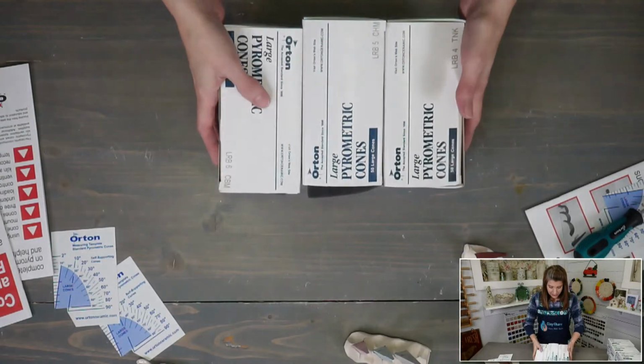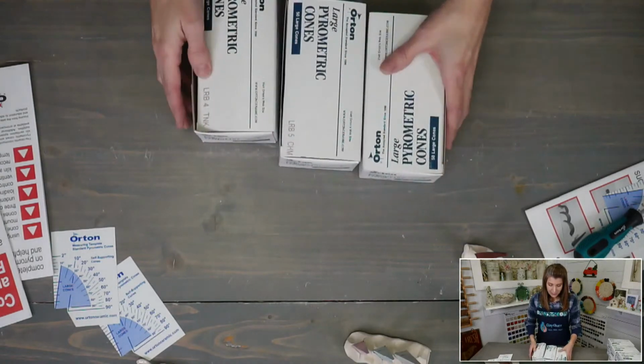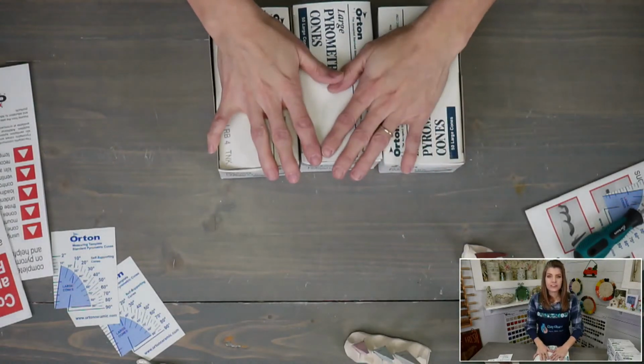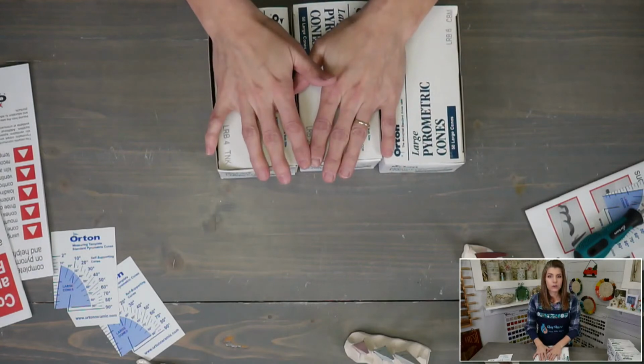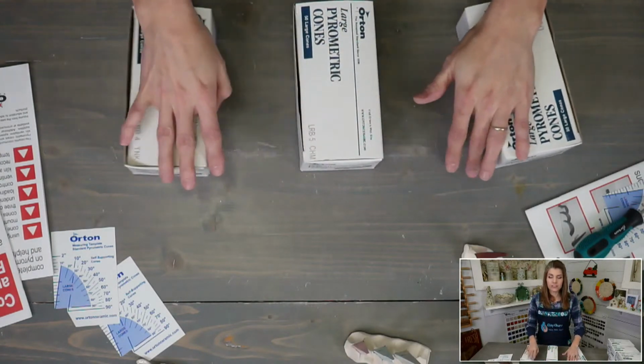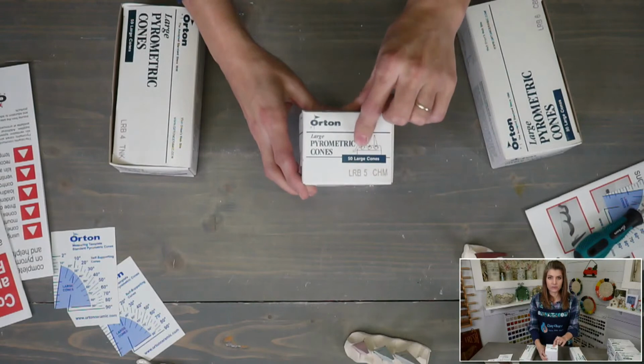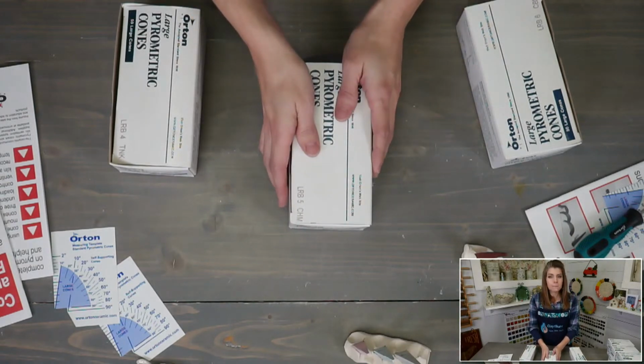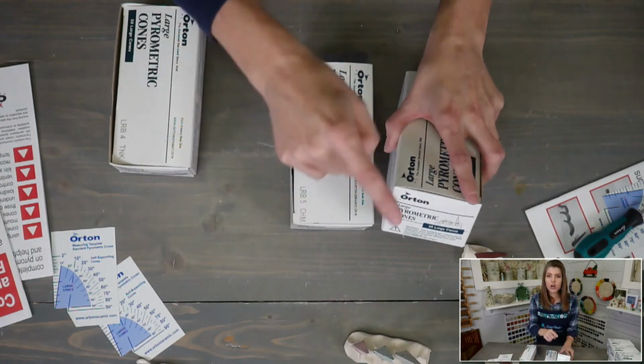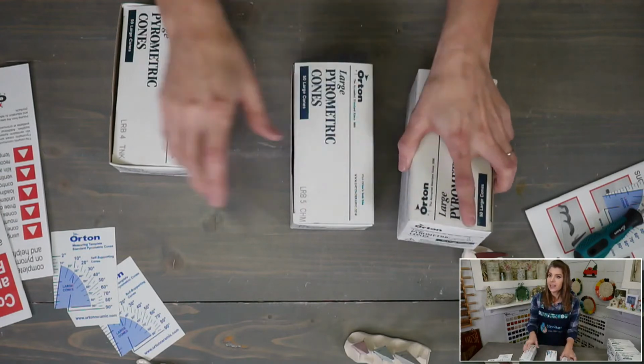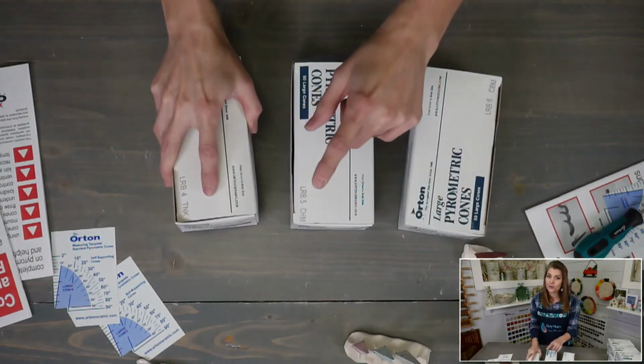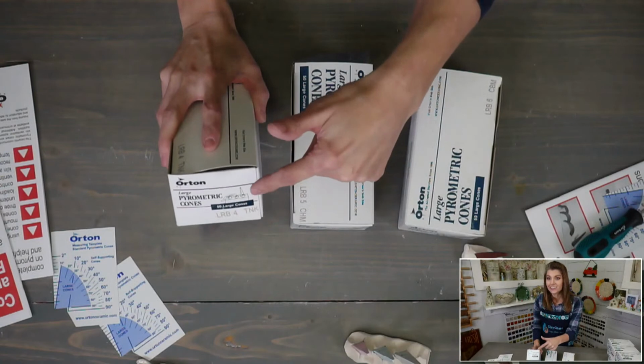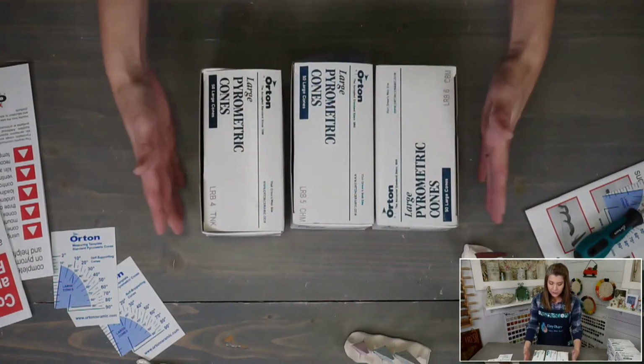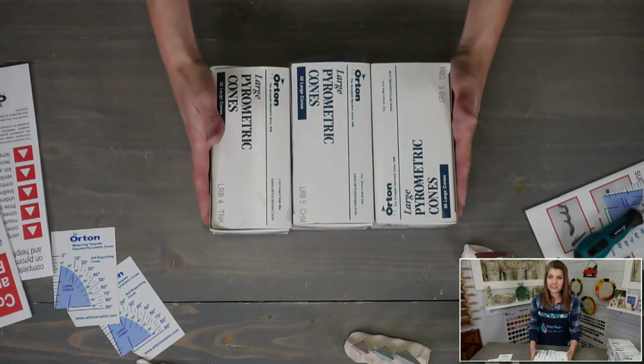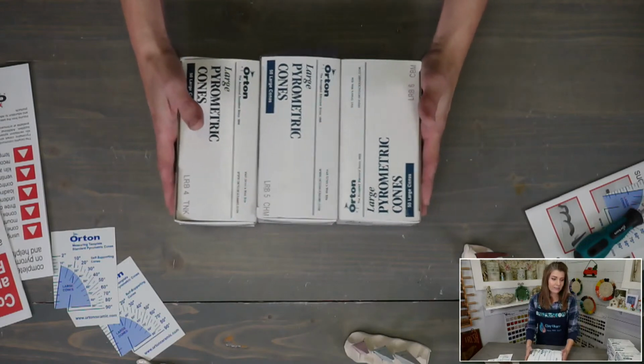Okay, so let's talk about the cone packs. What temperature are you firing to? Well, I'm firing to cone 5. So if I'm going to fire to cone 5, that's my target cone. Then I need my guide cone. That would be 1 cone lower, cone 4. And then my guard cone, which is 1 cone hotter, right? So we have our 3 cones that make up our cone packs for our glaze firing.